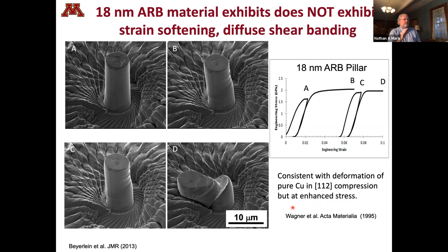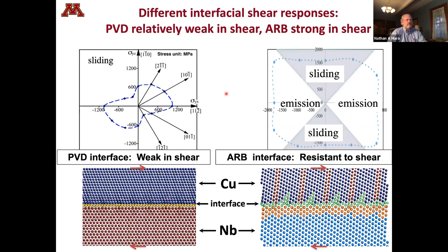If we wanted to contrast a little bit more between these two, we can take a look at some molecular dynamics simulations. We can compare the interfacial shear strength of PVD material versus our ARB material. And if we go with our PVD material, so this is a map looking down onto the interface. If you were to now shear that material in any one of these directions, you will have an interfacial shear strength associated with shearing in that direction. And that's this blue dotted line. What you find is that in some directions, it's only a couple hundred MPa, which is very consistent with what we measured in the transmission electron microscope. So hey, you got modeling and experiment coming together here, life is good.